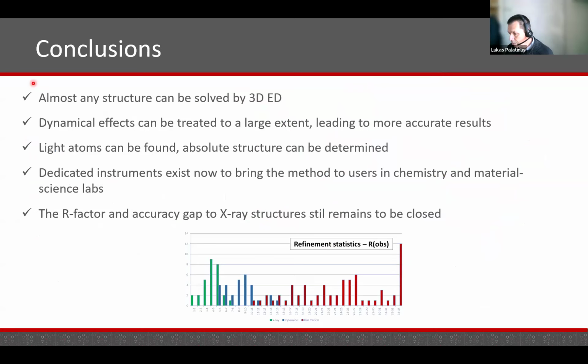So with this, I come to the conclusions. I want to reiterate that nowadays, almost any structure can be solved by 3D electron diffraction. There are no limits on complexity. Even protein structures are being solved nowadays. I haven't spoken about macromolecules because this is not my field of expertise, but there are people analyzing macromolecular structures with 3D-ED. The largest complications are the dynamical effects, but they can be treated to a large extent, and that leads to more accurate results, finding light atoms even in the presence of heavy atoms, and determining absolute structure of non-centrosymmetric materials.